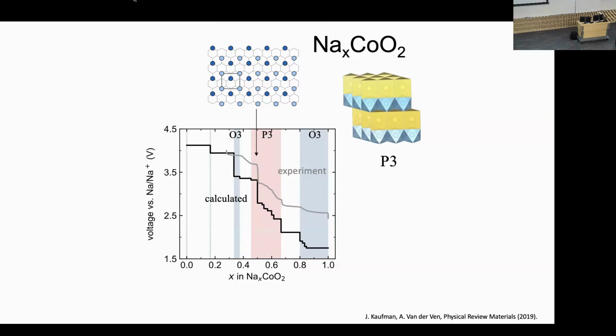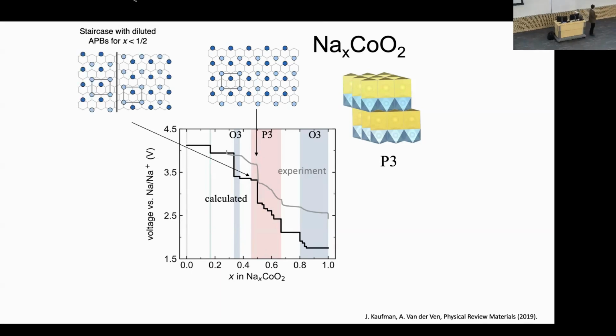With oxides, DFT also has a systematic error, and that leads to a systematic shift in the predicted voltage. But you can see that the relative variation agrees very well with experiment. So the same phenomena are happening, it's just a constant offset. And with the oxides, it really likes this ordering at 50%. This is at half, and this just maximizes the separation of the sodium ions. And it likes it so much that if you try to disrupt it, it will again try to preserve it. So for example, that's why you have this big strong step. That's this ordering right here.